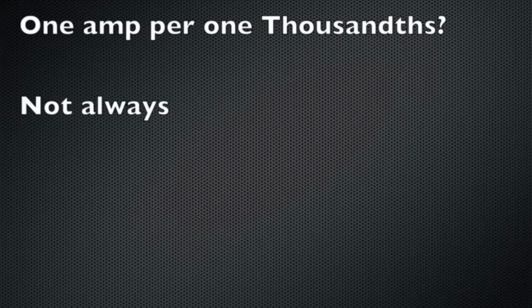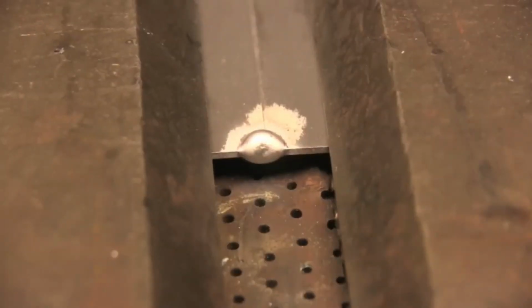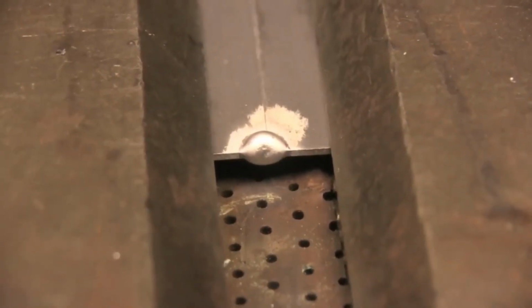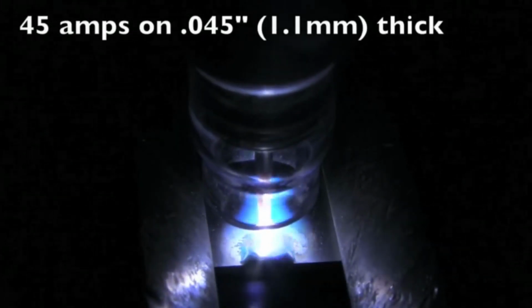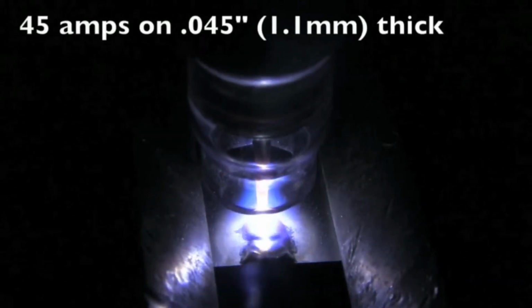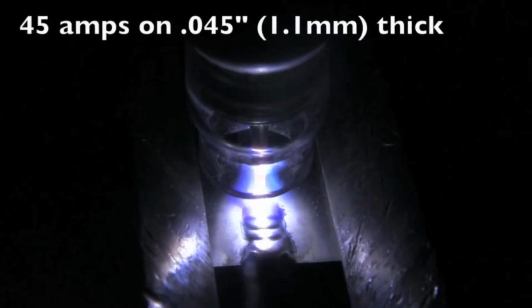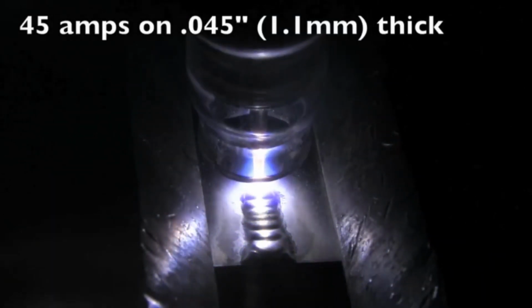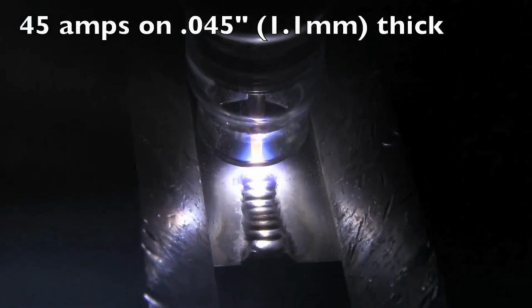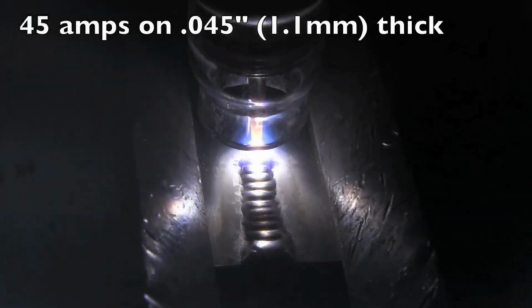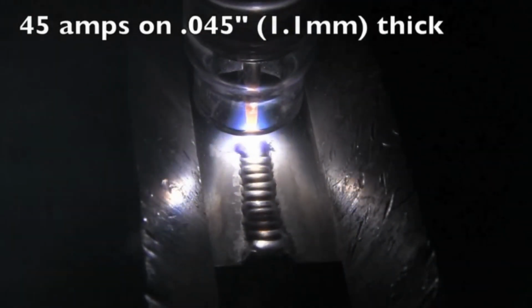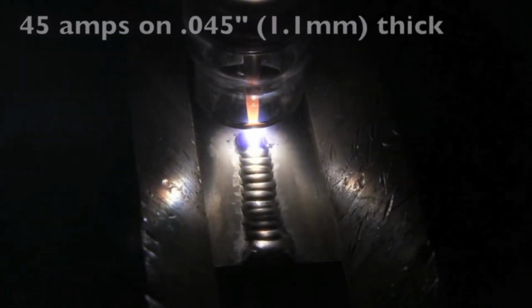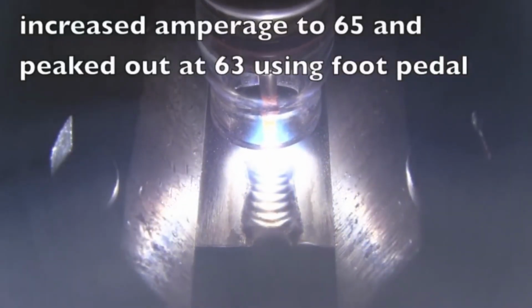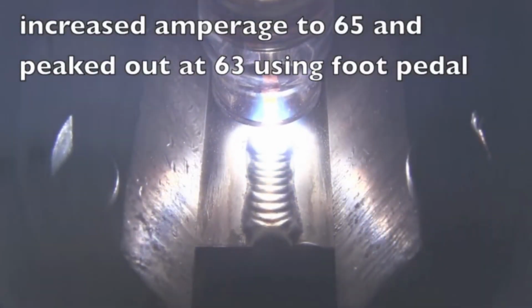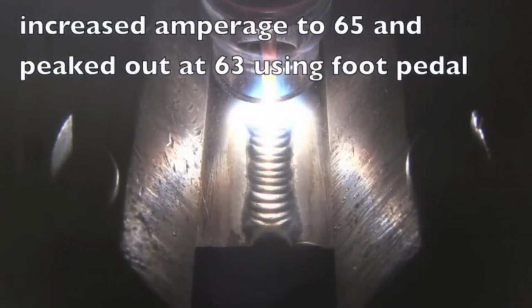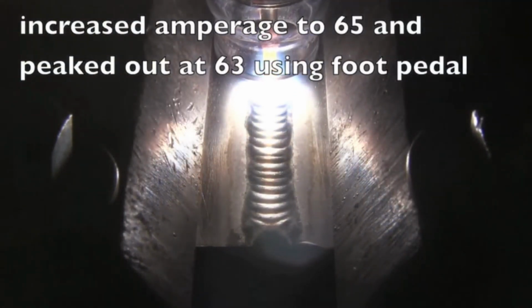If you use high AC frequency, you're going to need a little bit more amperage a lot of times. And also when you have chill factors, like this is in a fixture, even though it's only a carbon steel fixture and it's not pulling a tremendous amount of heat out, it still is pulling heat out and requires more amperage. This is an example. 45 amps on 45 thousandths thick metal, and you can see it's very cold. It's just laying on top. Had to increase it to 65 and actually peaked out around 63 using a foot pedal. That was about right.